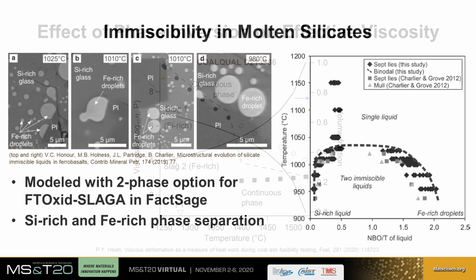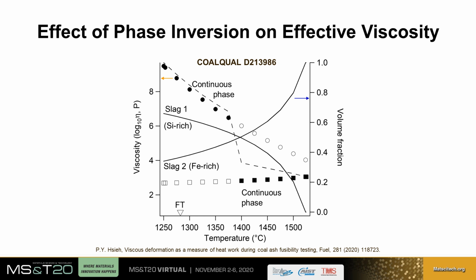The modeling results suggest that a phase inversion between the silicon-rich and iron-rich phases may lead to an abrupt discontinuity in the effective viscosity of the molten silicate phase above the liquidus temperature, where no solids are present, while phase inversion has been observed for oil and water emulsions and water and oil emulsions. The discontinuity in viscosity as a function of temperature has not been verified for molten silicates in the lab, at least not yet.